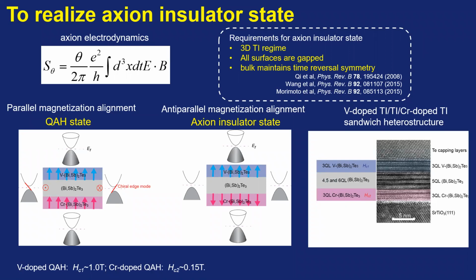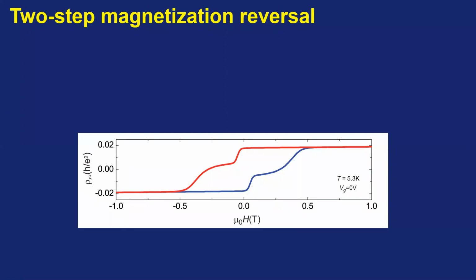So this is the TEM image of our sample. We can clearly see this is 3 layer, this is 4 layer, and this is the 3 layer vanadium doped TI. So this kind of anti-parallel alignment sample, we call it axion insulator sample, axion insulator state. In order to confirm there is anti-parallel alignment in this kind of quantum anomalous Hall sandwich structure, we take the MFM measurement and the in situ transport measurement.